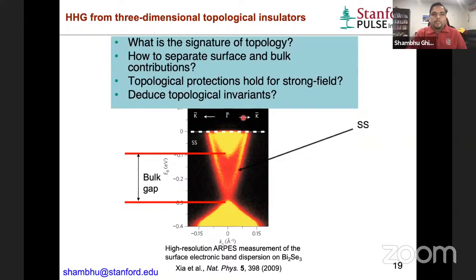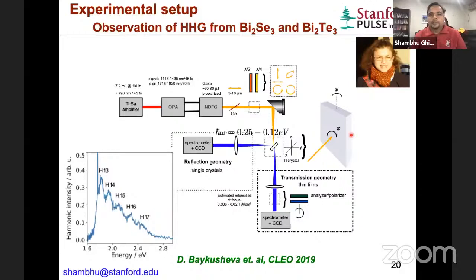In order to realize this experimentally, Danica Baykusheva put together this nice experimental setup, and she was able to produce a tunable mid-infrared laser field and do these experiments. She took thin films, single crystal thin films, and did experiments in transmission, and freshly cleaved bulk samples in the reflection geometry, because bulk samples absorb the harmonics. So this is one of the measured spectra that has both odd and even order harmonics, and that becomes really useful.